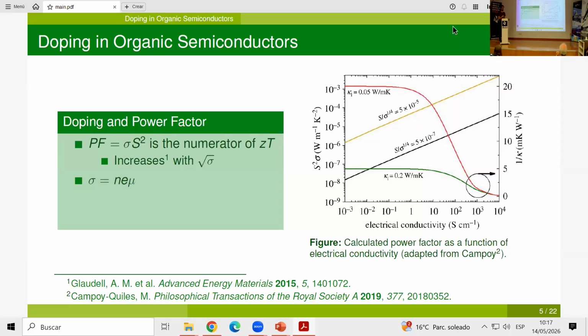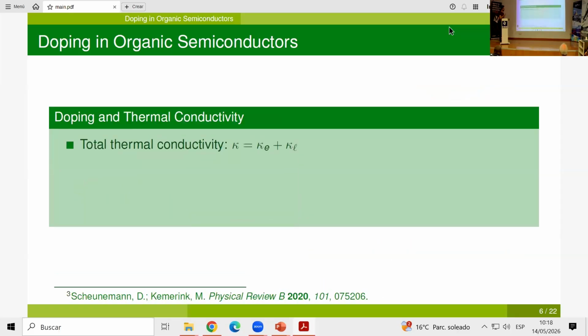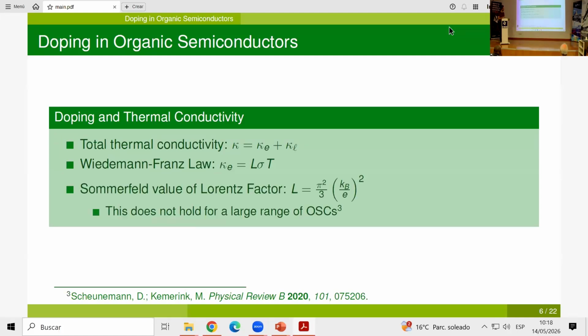So we all remember that the electrical conductivity is given by this expression where we have the charge carrier density, elemental charge, and mobility. But S is inversely proportional to the charge carrier density. So we need to improve mobility to improve the power factor. Whereas total thermal conductivity is given by the sum of an electronic contribution and a lattice contribution. We normally use the Wiedemann-Franz law to connect the electrical conductivity and the electronic contribution to the thermal conductivity. However, this does not hold for a large range of organic semiconductors.